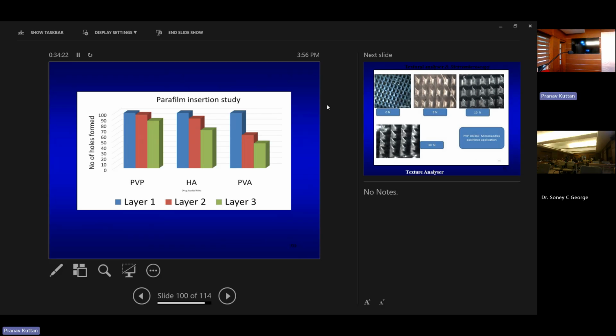Then this was one skin mimicking study which we performed. That is parafilm. Parafilm is generally considered as a skin mimic actually. We will fold it 8 times to get a skin kind of structure. And there's an equipment called a texture analyzer. You put the microneedle and apply a particular force. It will go and punch that skin. So we will see how many holes are being formed. We saw that PVP and HA are found to be good in forming holes up to layer 3. That means it has that penetration ability.